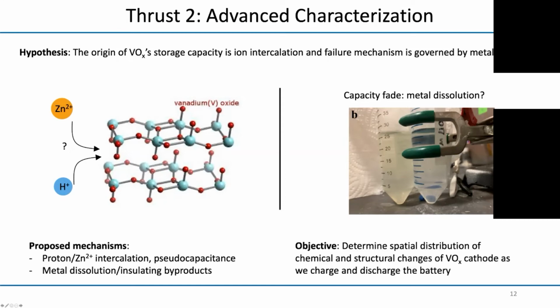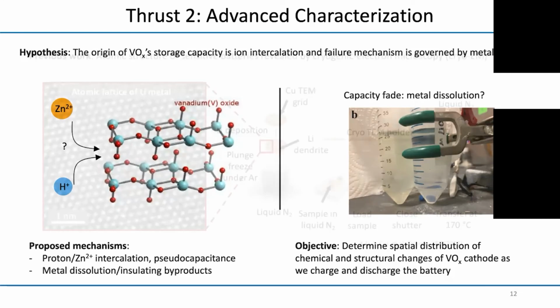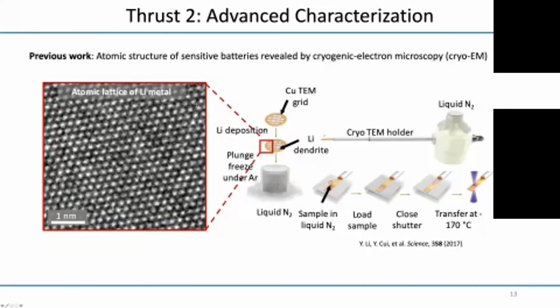And so our objective is to really use our advanced characterization tool to determine the distribution of chemical and structural changes in our vanadium oxide material as we charge and discharge the battery. And the technique we want to use is the cryogenic electron microscopy. This technique we showed is very, very effective in characterizing sensitive battery materials. Back in my PhD, we were the first to demonstrate this technique for lithium metal anode, where we showed the atomic columns of lithium for the first time, demonstrating that under cryogenic conditions, these sensitive materials are stable under the electron beam.